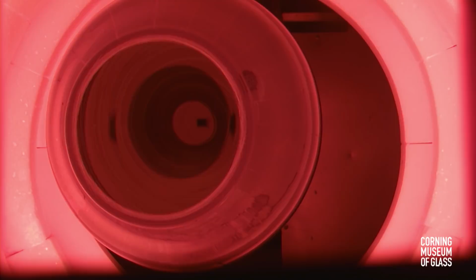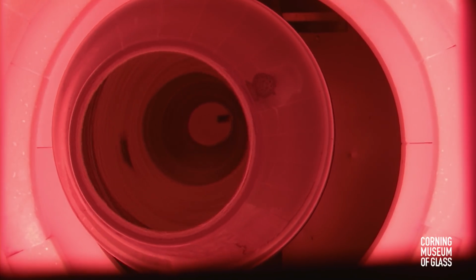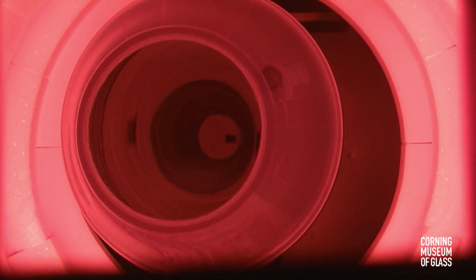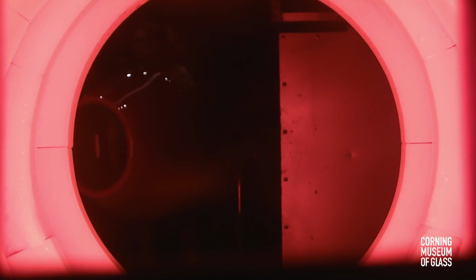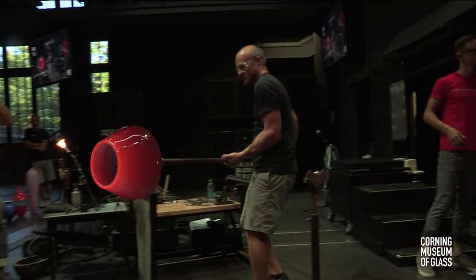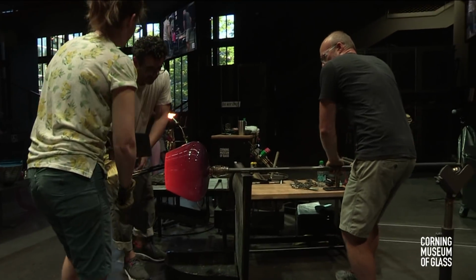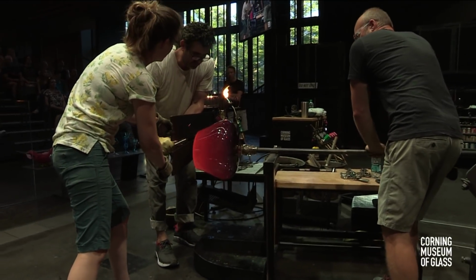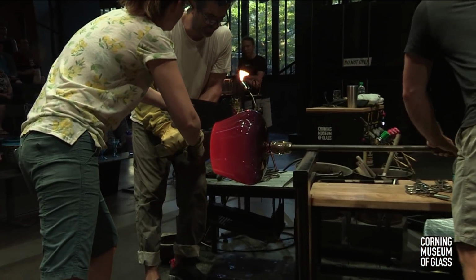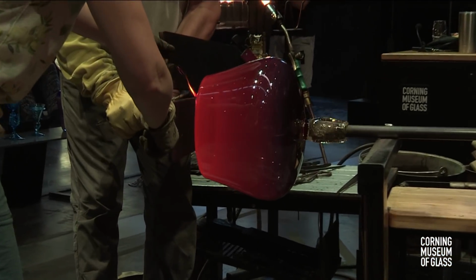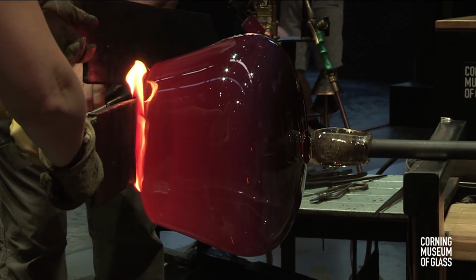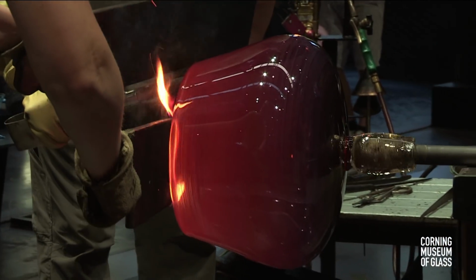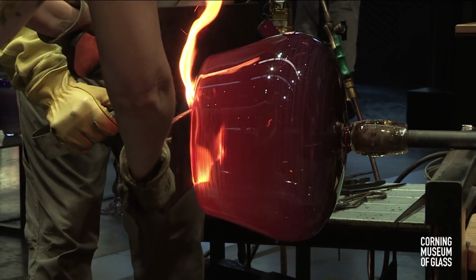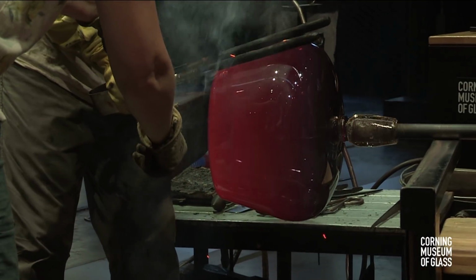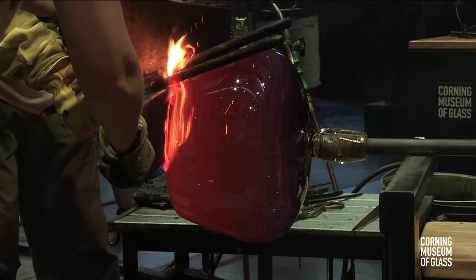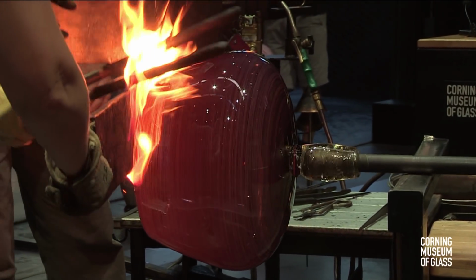So we know from reheating out of that oven every single day, day in and day out, where the hot spots are in that furnace. So depending on how far in or out you go, you get that bubble position right in front of the burners and get the heat that you're looking for. The longer you stay in there, the hotter the glass gets. And with a bowl like this, it's really important that we turn very slowly. Because if he got this whole thing hot and he was turning fast, the hottest parts start to flare out. And we don't want this to flare out. We want this to stay a nice, low, curved bowl. So you have to exercise a lot of control in your heats and the turning.